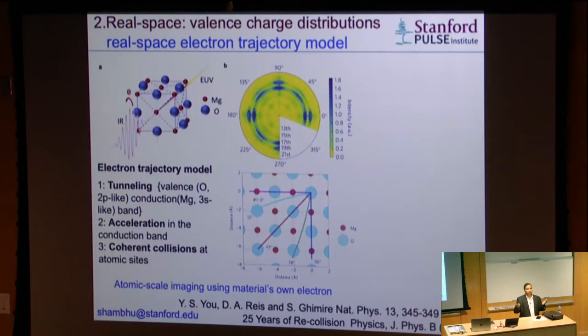Of course, there's a lot of details there, but I just wanted to get the message across, using this very illustrative, semi-classical picture. Now, in real space, we spent some time in real space. We used the magnesium oxide crystal. And this is also a very simple experiment. All you do is you take a crystal and you rotate the crystal and see how the efficiency of harmonics changes. And this is the raw data.